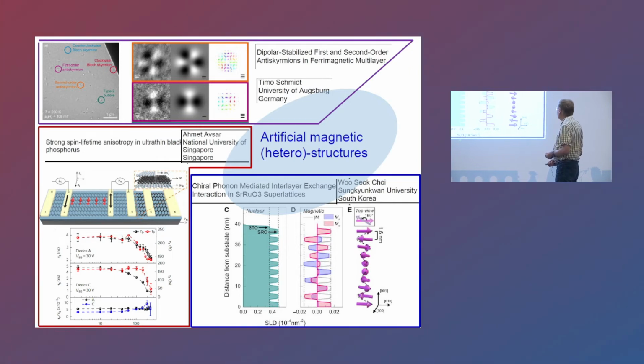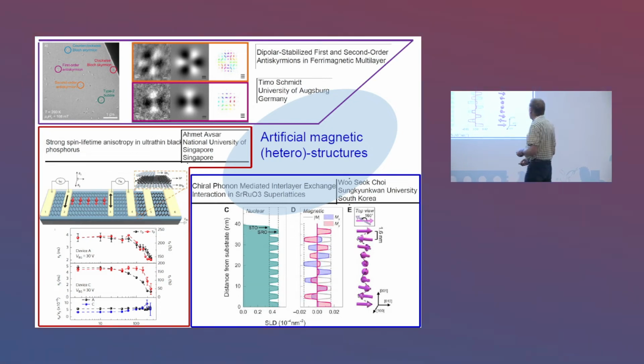Another kind of heterostructure where these chiral interactions were considered and experimentally observed is a multilayer built out of ferromagnetic strontium ruthenium oxide separated by thin layers of non-magnetic strontium titanate. The magnetic structure of this multilayer was revealed to be of spiral character, and it was argued that this is a novel kind of phonon-mediated interlayer exchange which gives rise to these non-collinear spin structures.